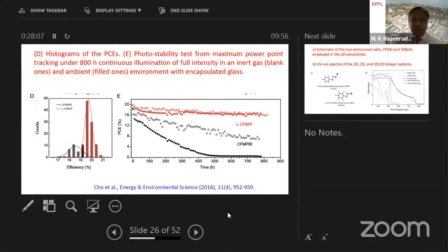Yeah, so this slide shows the stability data of the reference sample. That's a pure perovskite solar cell without any two-dimensional perovskite. The red line shows the stability data over 800 hours of the perovskite solar cells deposited with the two-dimensional perovskites.